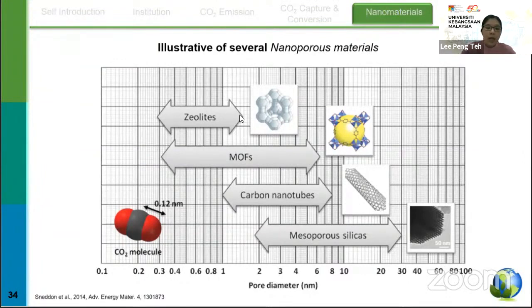And over here we have zeolite. Zeolite is one type of aluminosilicate material. We have aluminum and silicon forming frameworks, so we have SiO-Al frameworks. Zeolites have acidic properties and basic properties. For CO2 capture and conversion, we are concerned about the basic properties. The basic properties of zeolites arise from their ion exchange properties, as well as their silica alumina ratios. Another factor that I would like to emphasize here is the porosity. In CO2 capture and conversion, the porosity is very important.